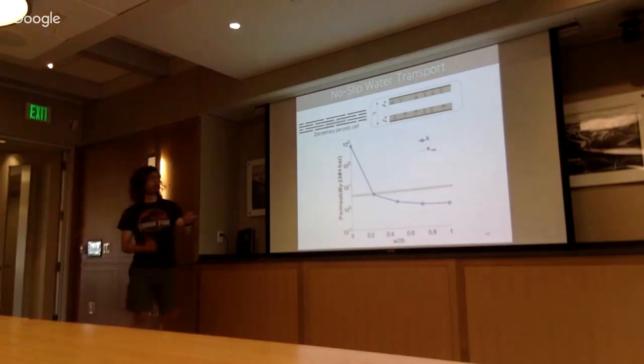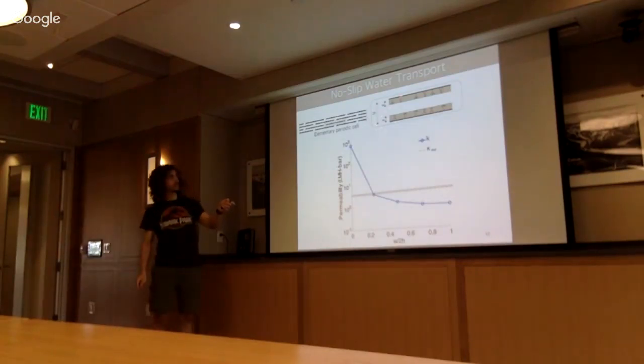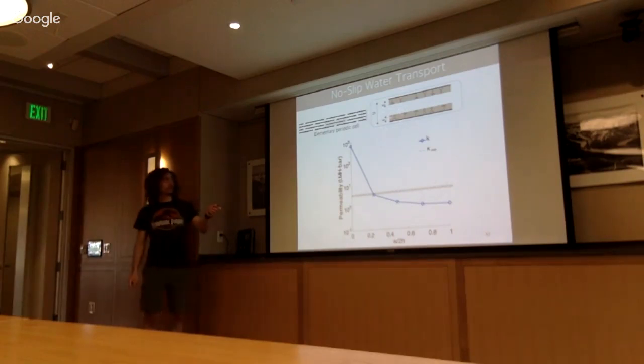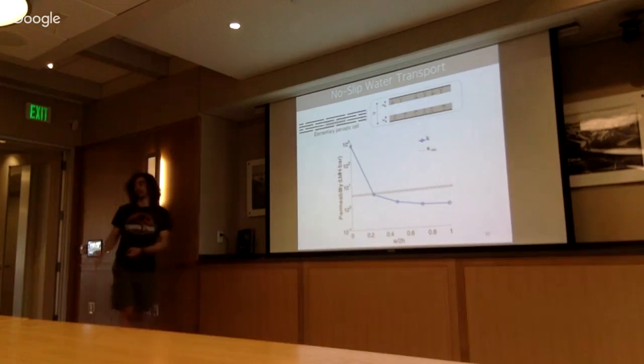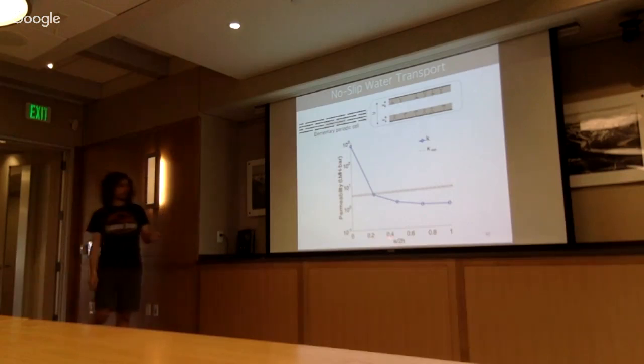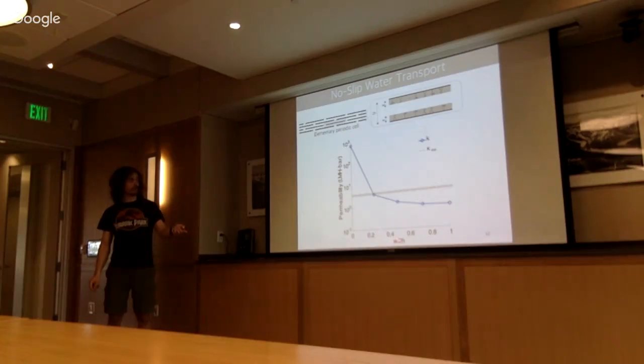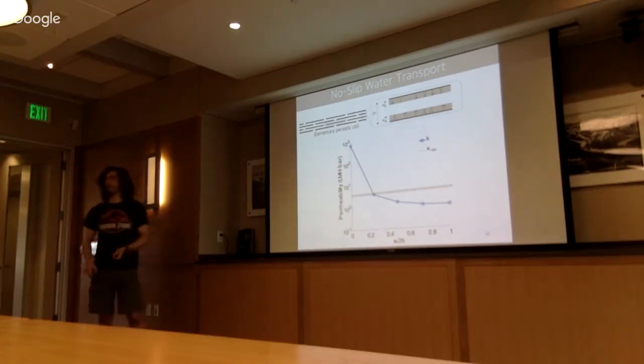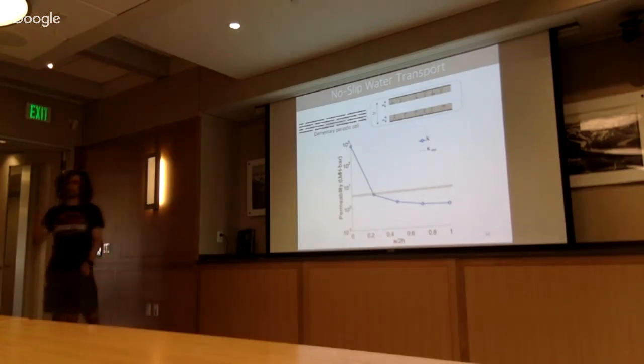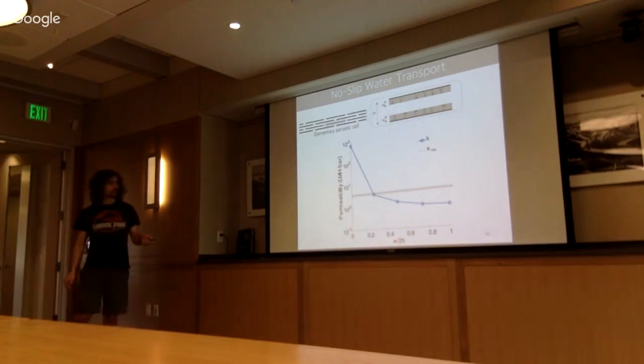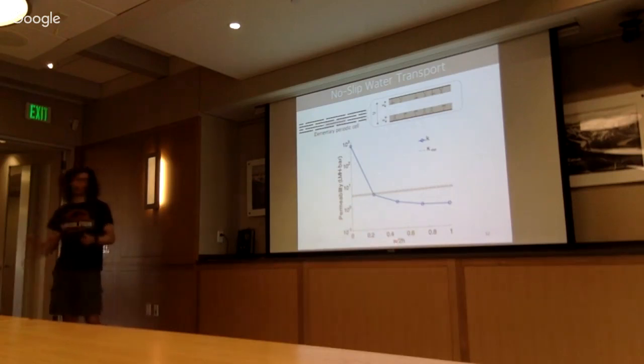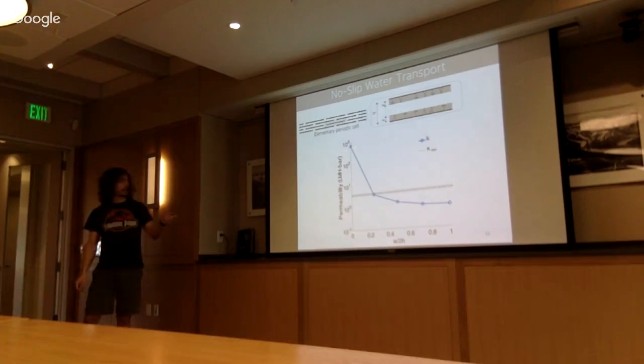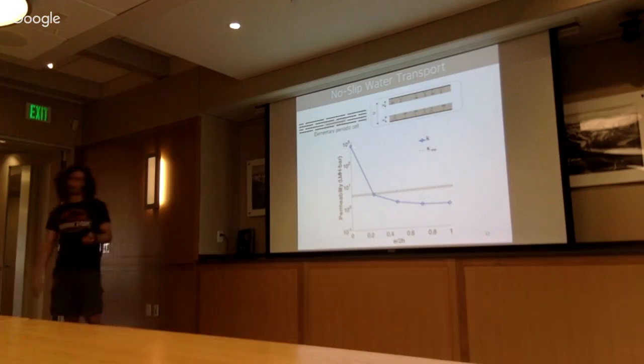What I want you to pay attention to is that the separation distance between the flakes is defined as 2h, whereas the extent of the friction is W. Here I'm plotting the ratio between W and 2h, and here is the permeability, so how much water goes through the material. When W is equal to 0, there is no friction, and we obtain a permeability of about 1,000 LMH per bar.